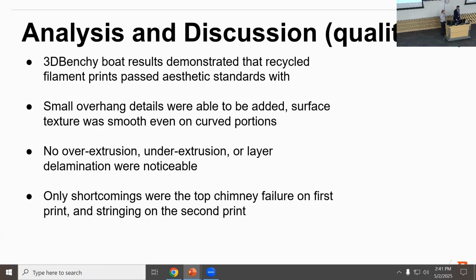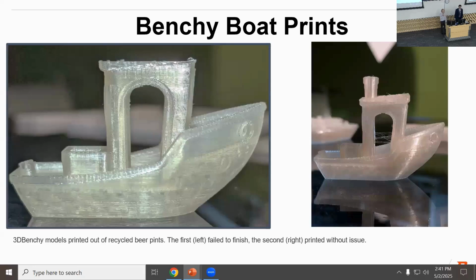As for the qualitative analysis, the 3D Benchy boats demonstrated that this material can be printed into some useful aesthetic parts. The small overhang details were able to be added very successfully. The surface texture is very smooth, no under or over extrusion. The only shortcoming is that the very first boat we printed on the left didn't finish.